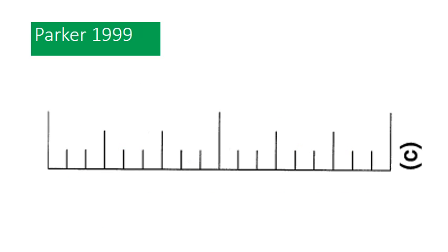Now, when you go through the logic of the cracking and shedding sequence, Parker's going to predict a fairly regular pattern in the depths of cracks, and that pattern is going to be based on the spacing ratio. So if you look at these, it kind of looks like you're looking at a ruler, but rather than looking at inches and half inches and quarter inches, you've got this 3-to-1 spacing ratio.